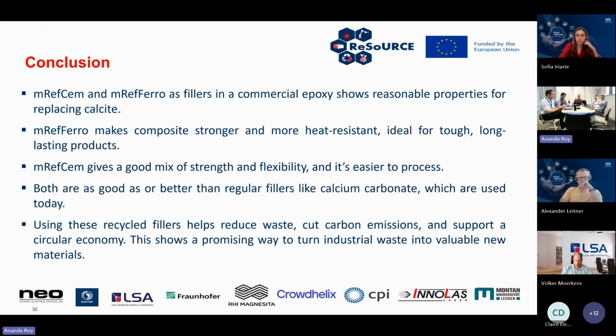Now, there was a lot to cover within the application base, but we have only reached out to what we thought was appropriate within the system. But you can see as a conclusion that MREF ferro and mRefCem within the commercial epoxy base show reasonable properties for replacing the standard filler of calcite that we have used to show that comparability. Furthermore, MREF ferro makes the composite much stronger and much more heat resistant, which is ideal for tough, long-lasting products. mRefCem has a good mix of strength and flexibility, and it's much easier to process during the manufacturing of these polymer systems.